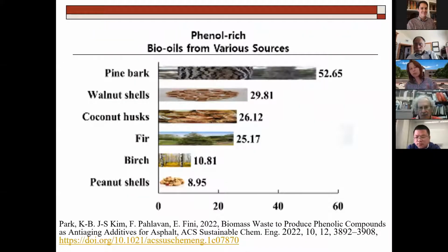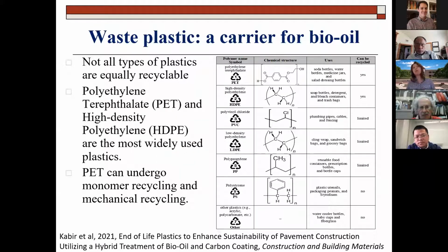Stopping one second here, these phenol-rich oils need to be dispersed in asphalt to be able to work. You can't just put it in a corner. It has to be everywhere. So what we did here, we used a carrier for it, which is funny in a sense that I'm not advocating plastics production, but plastic now is everywhere, right? We talk about waste plastic being so problematic and so forth. Some of those plastics I'm showing you here are recyclable, some are not. In this case, we actually used PET for one scenario as a carrier for oil, and we attached our bio-oil onto the plastic and then dispersed it into the entire asphalt. I'll show you the results.